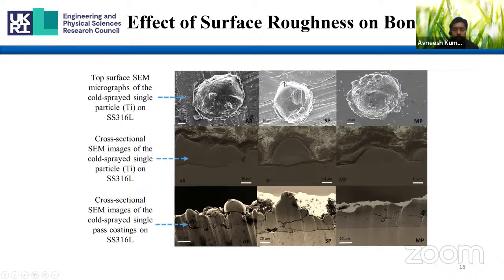And we have seen that in all the cases there was jetting, but the jetting was most significant in the case of mirror polished surface. Then it was minimum in the case of semi polished surface, and there was some jetting on as received surface as well. As we have discussed above in the bonding mechanism, the jetting is the main reason for the bonding. So to further see what is happening at the interface, we did some cross-sectional SEM image analysis of